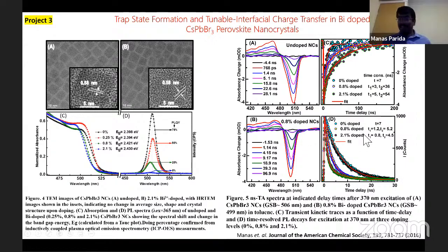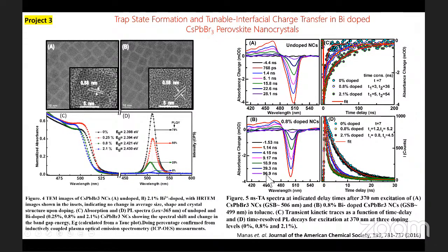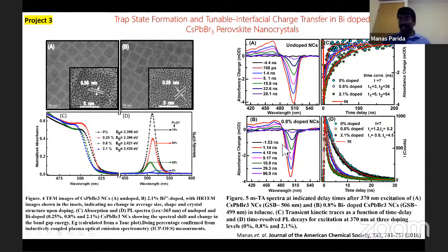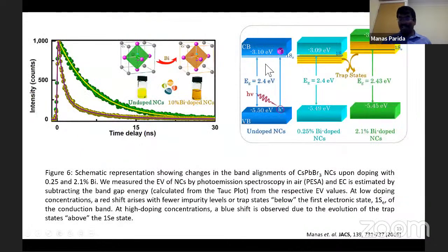If you compare undoped and doped, we already said the doped recombination is taking a higher time. But if you compare with the PL lifetime, this is the absorption lifetime measured here, and that is the emission lifetime. The emission lifetime always goes to a faster recombination rate, meaning it is decreased. Here it is increased, and here it is decreased. These are two different measurements: transient absorption here, and PL there. So how do we explain that?